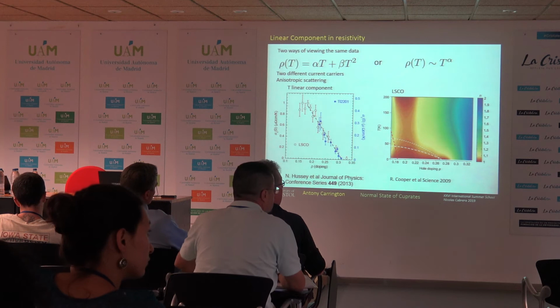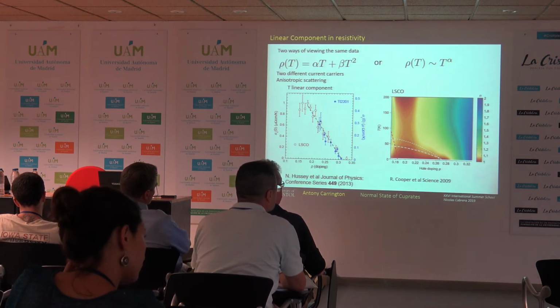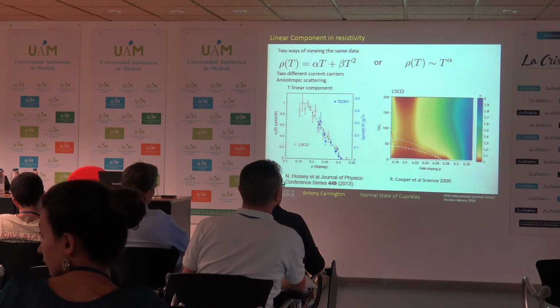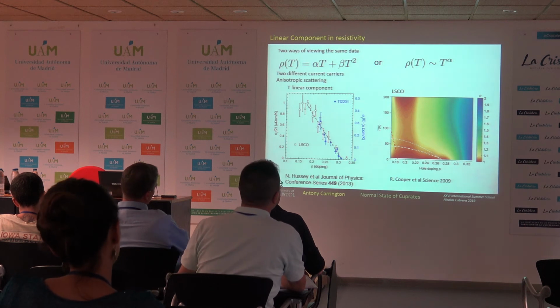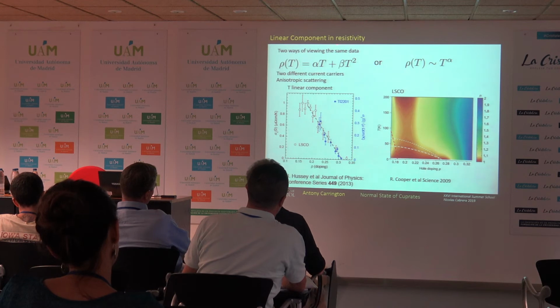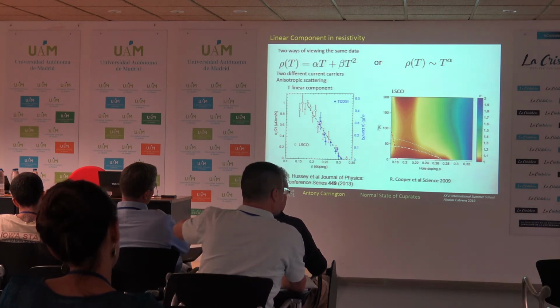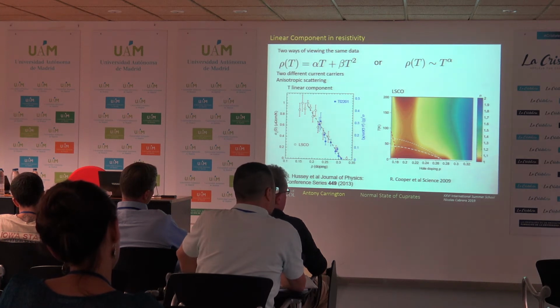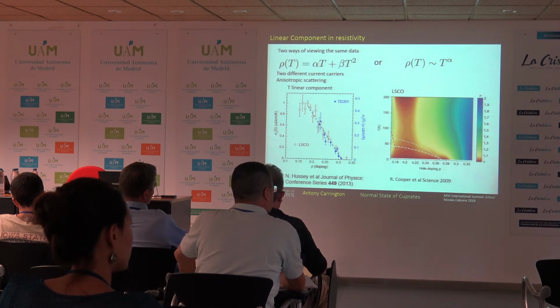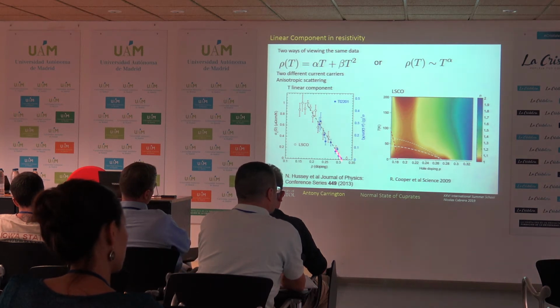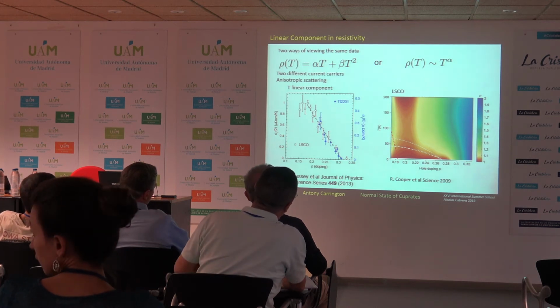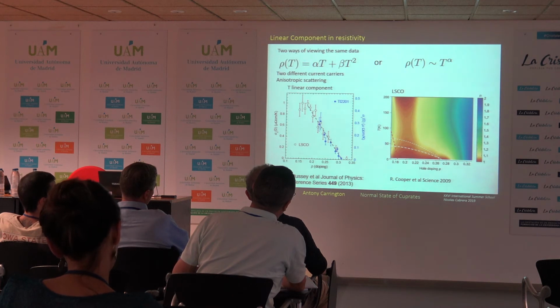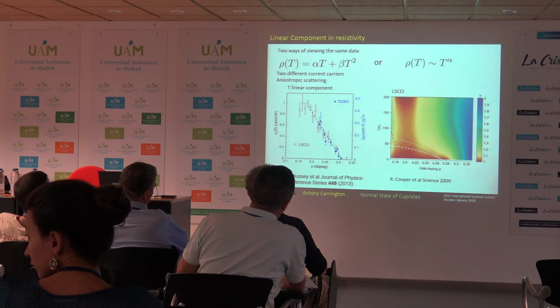So you're saying if I divide the scattering rate by k_B T. Correct. Yes. So everybody says that the coefficient is 1. So h bar tau to the minus 1 is k Boltzmann T. So the caveat here, Jorg, is it may depend on how you interpret this. If you interpret this as being a scattering rate on a piece of Fermi surface, for example, then that could be true, right? So it could be that that piece of Fermi surface at the Planckian limit is growing. So if I average it over the whole Fermi surface, the answer is definitely no, right? Because obviously this is changing. Right? But another implication of these beautiful data is that we do not have a quantum critical point. We have a quantum critical phase. Yes, indeed.